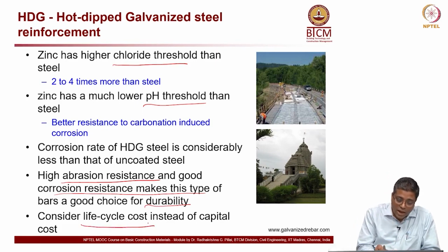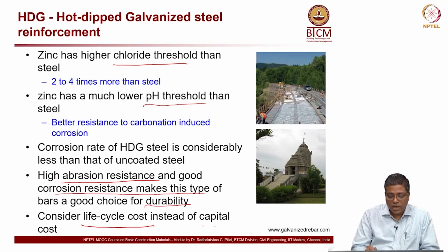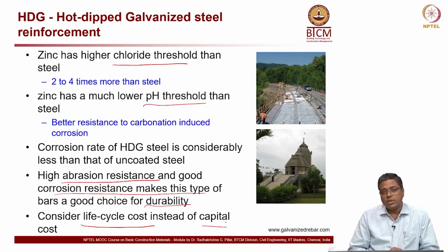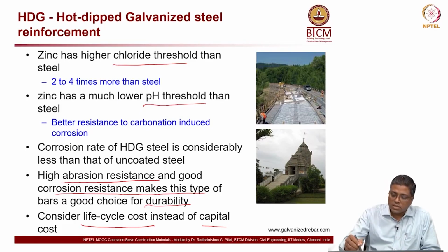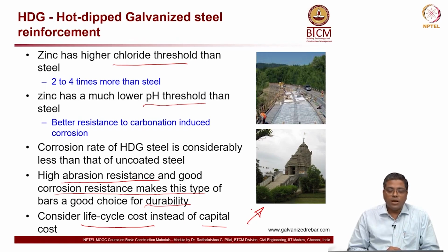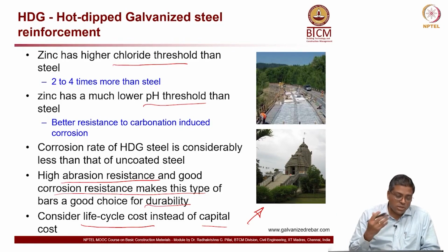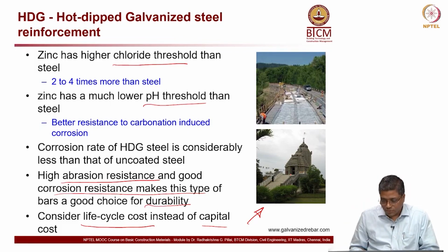But if you look at life cycle cost instead of the capital cost, then you will see that these kinds of bars are actually durable, and beneficial in the long run. Life cycle cost. So, these are some examples. This photograph is from a temple in Chennai where they have used galvanized steel, and this temple is about 50 to 100 meters from the seashore, very close to the seashore. So, this was the only option to really have a long lasting structure.